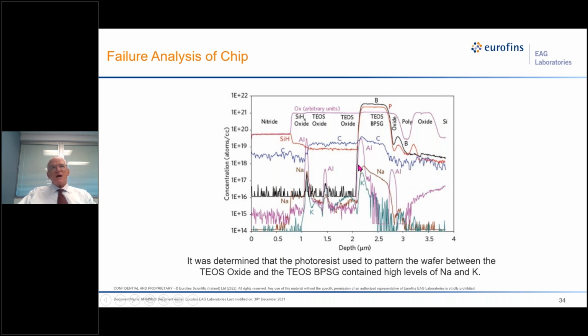In this particular spot, we see a lot of sodium and potassium were introduced. We learned later that the photoresist used at this step was contaminated with high levels of sodium and potassium. And these were driven in when plasma etching was used to remove the aluminum. They changed resist, and we analyzed some more, and this problem went away. So this is analysis with charge compensation, mobile ion analysis. These are very difficult to analyze without moving them.